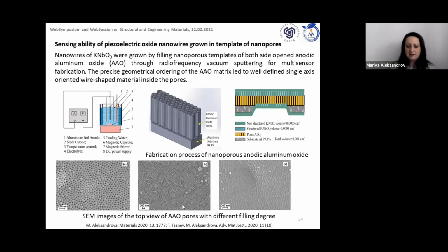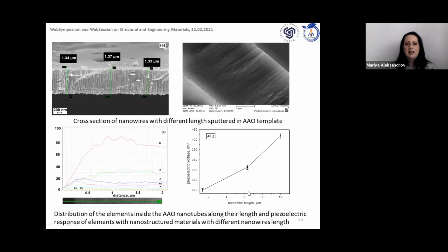potassium niobate. Here are the scanning electron microscopic images of the top view of the pores at different filling stages, different filling degrees, from open to intermediately filled to fully filled. And here is the cross section of the produced nanowires. Elemental scanning along the tubes shows that a uniform distribution of all components is available.